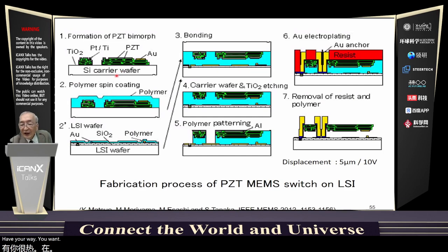Polymer is coated on it, and the flipped carrier wafer is bonded on the LSI wafer in three. After the carrier wafer is etched out, polymer is patterned in five. Gold is electroplated for electrical interconnection using resist as a mold. And finally, the PZT bimorph is released by removing the resist and the polymer.